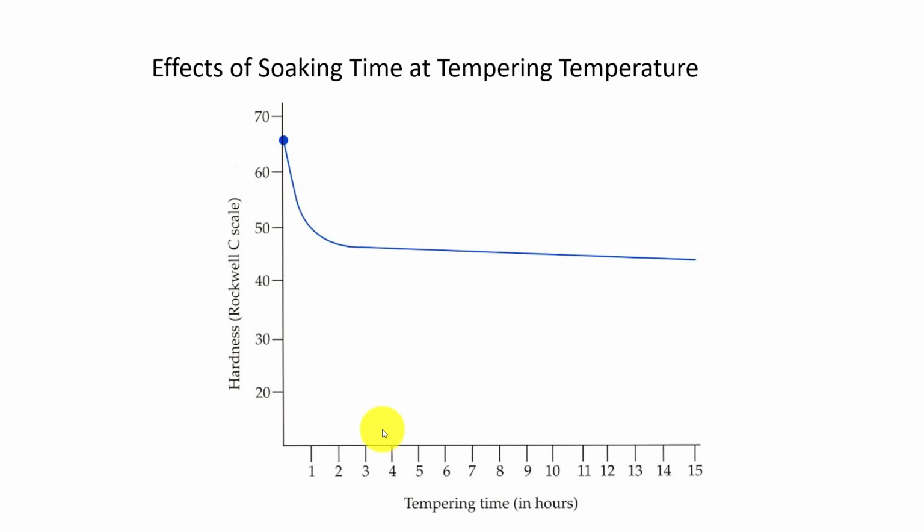This is the last slide, and let's talk about this before we get into the heat treater's guide. The thing is, how long do I leave the part in to soak? We talked about 30 minutes per quarter-inch section on a part to austenize it, and then we could quench it. And now let's say we want to temper it. So I'm going to put it in the oven, and I can still use that 30 minutes per quarter-inch cross-section formula, but how long do I leave it in the furnace? I need to leave it in there for some period of time. Okay, this is in hours.